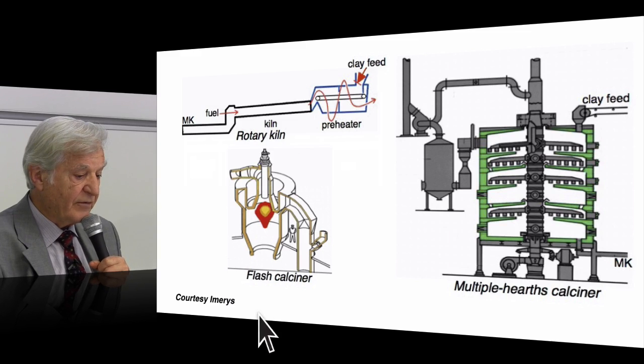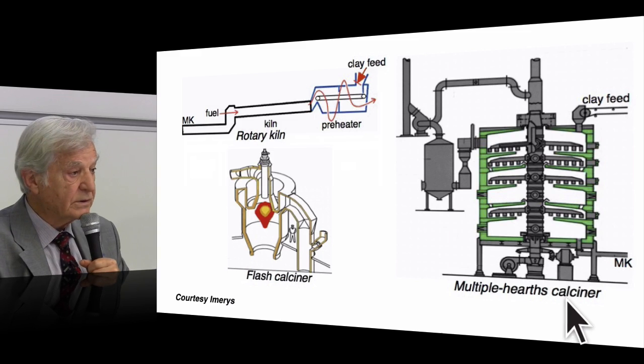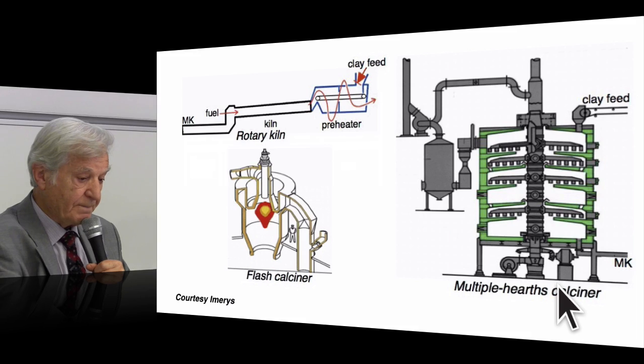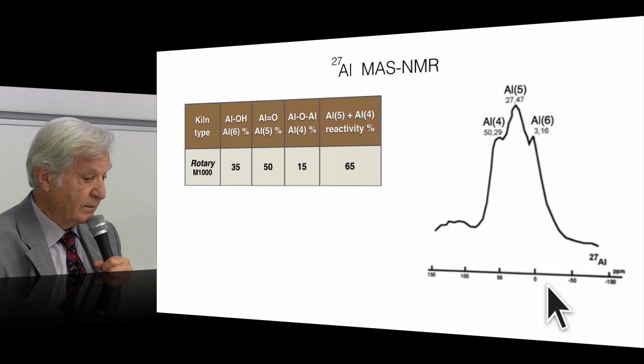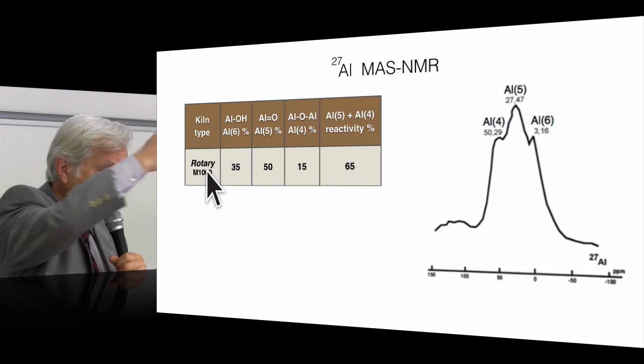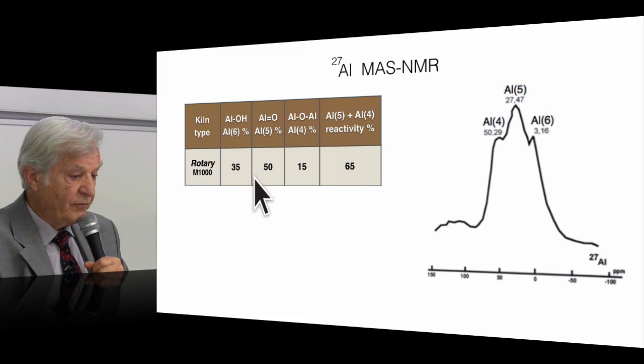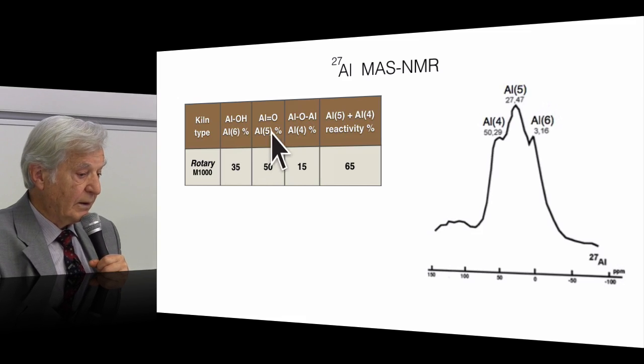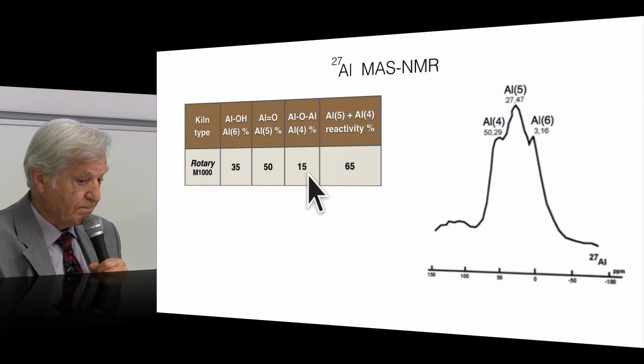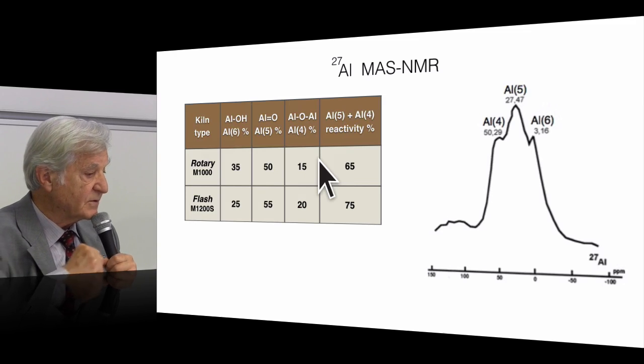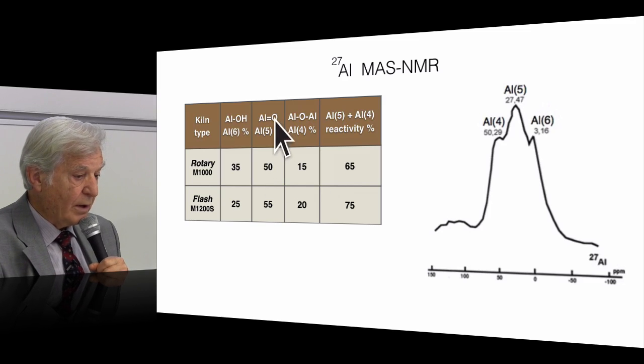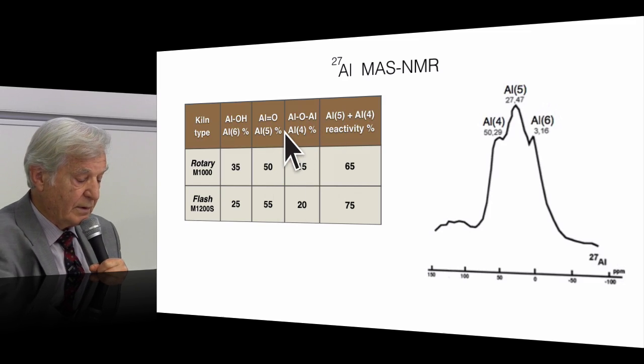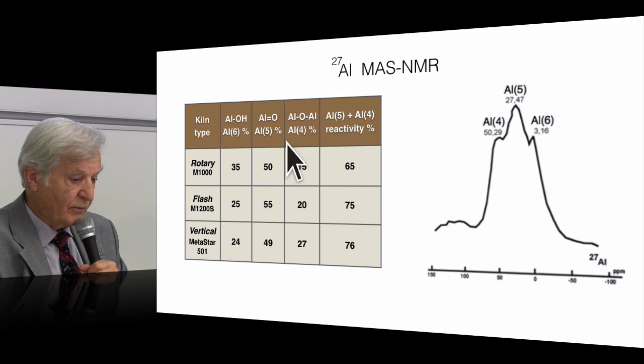You have rotary kiln, you have flash calciner, multiple hearth calciner. You have a presentation on this after my talk on that topic. So for the rotary calcination, that is the one that is in rotary cement kiln, we have a very high amount of ALOH, a high amount of Al=O, 50%, Al-O-Al only 15%. If you compare to the flash system that is super rapid, you have less ALOH, more ALO, and a little more of the reactive elements. If it is the vertical oven, then you also have less ALOH, Al=O, 49%, and Al-O-Al, 27%.